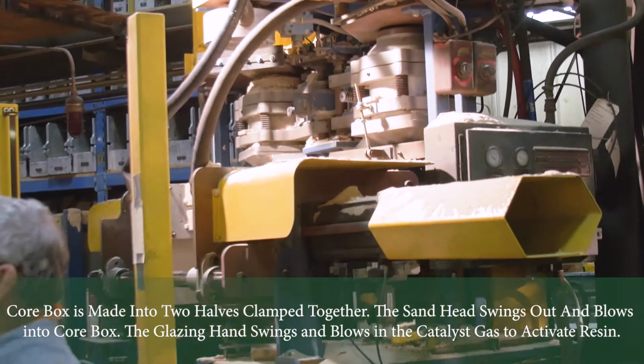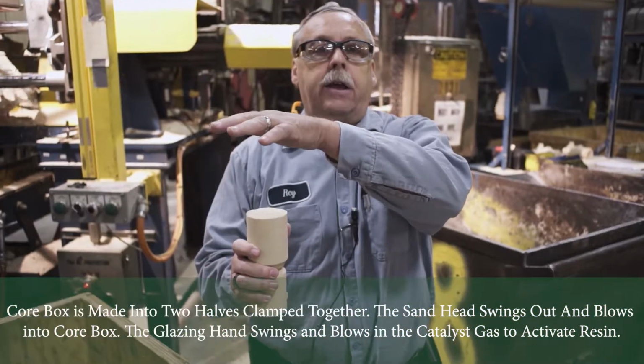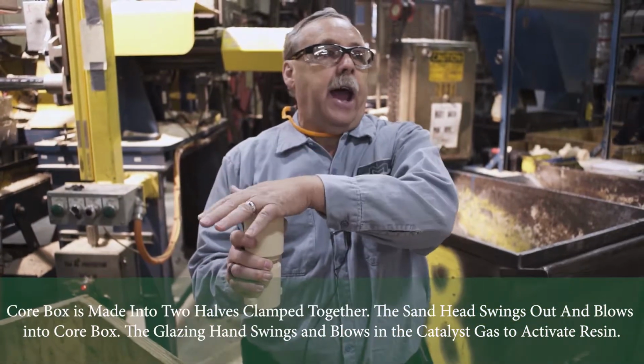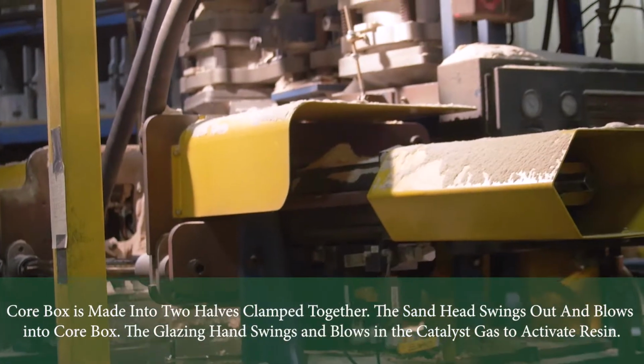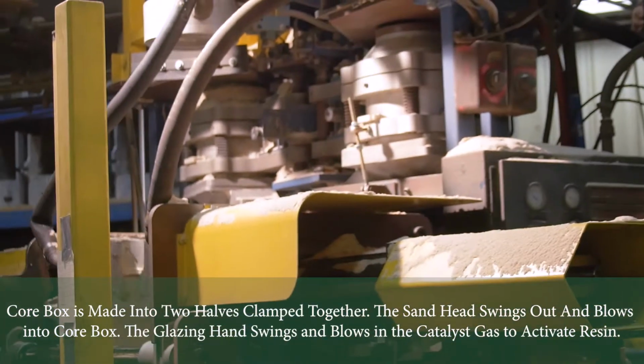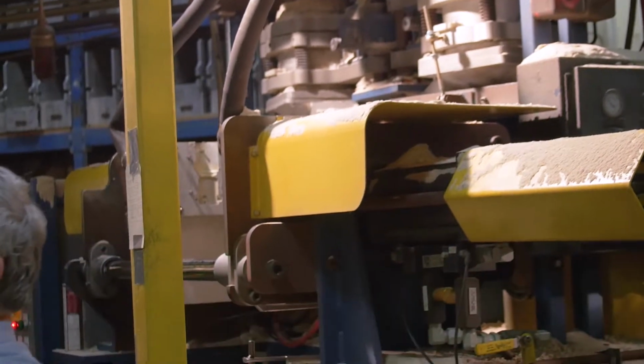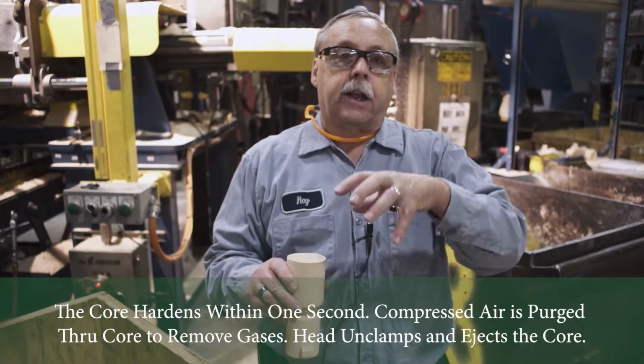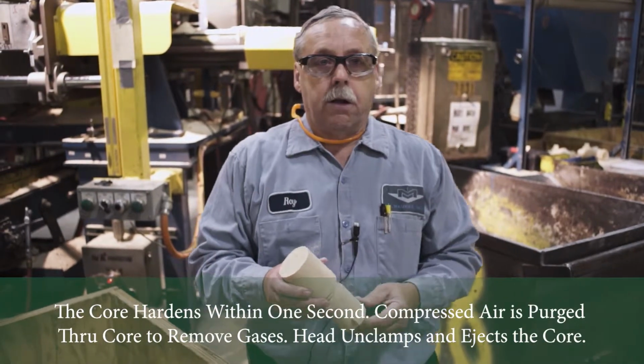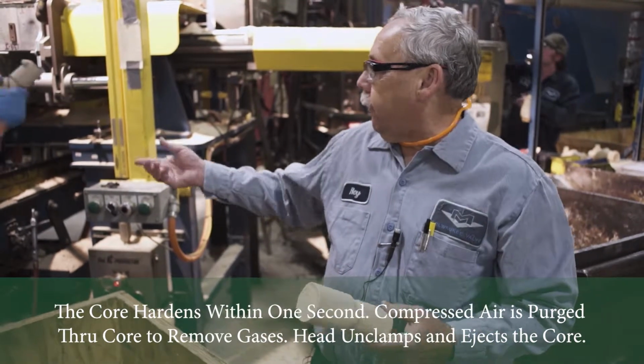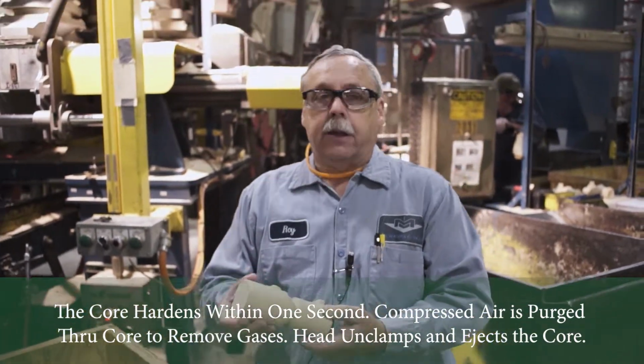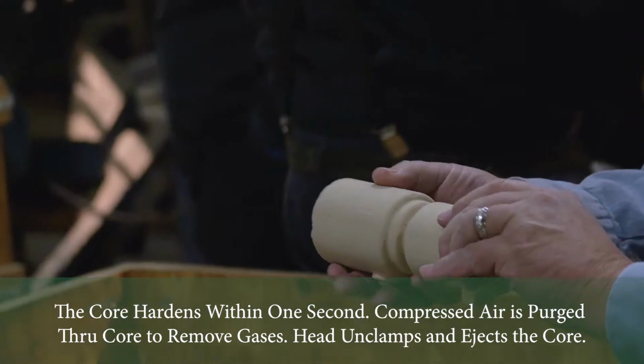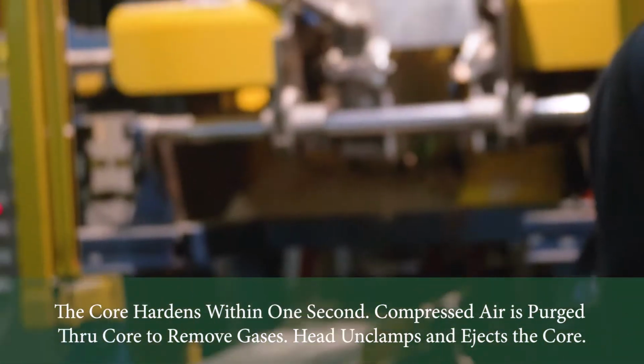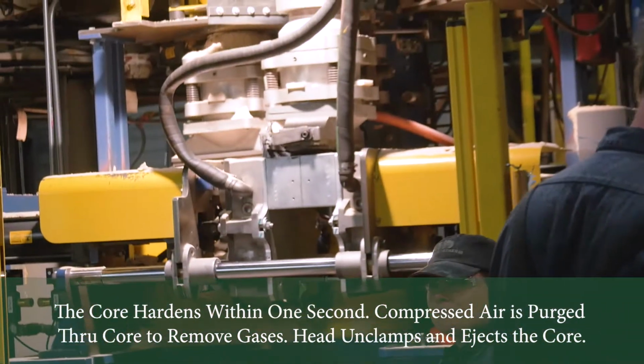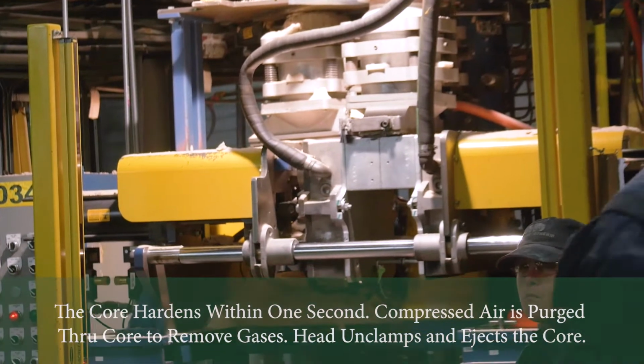We blow it into a box, clamped up, and then we bring a gassing head over and gas it with an amine gas, and that hardens the core very quickly, and then we add additional air to purge that gas throughout the core. And it's discharged for the operator, and he'll inspect it and trim off any parting line indications or anything, and inspect it and repair it at the time.